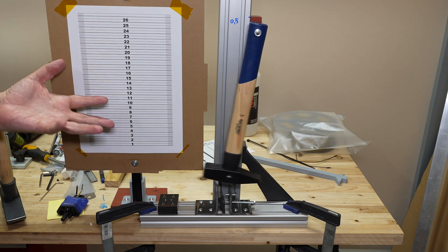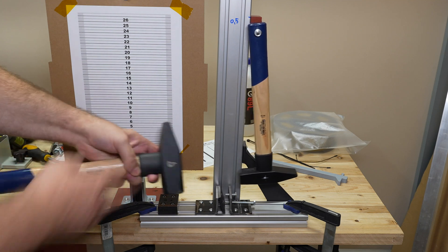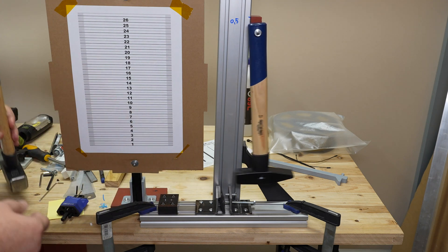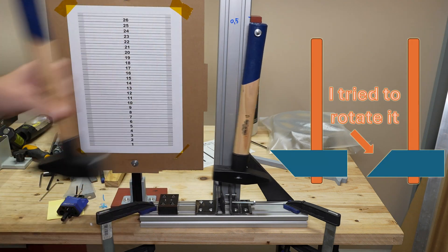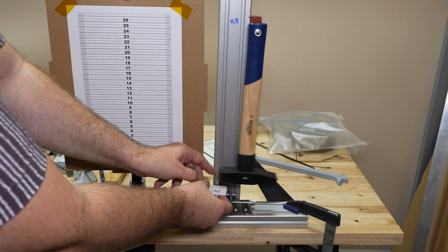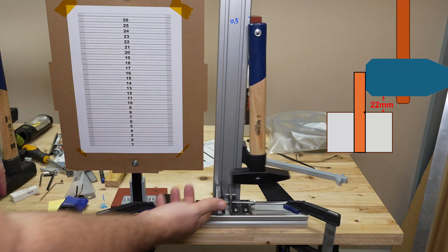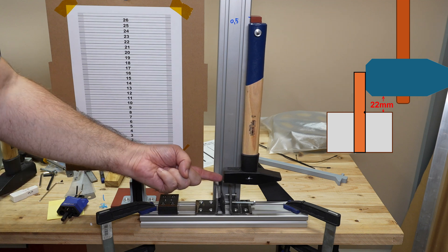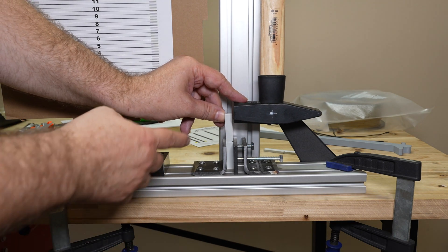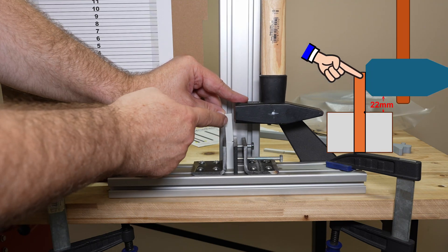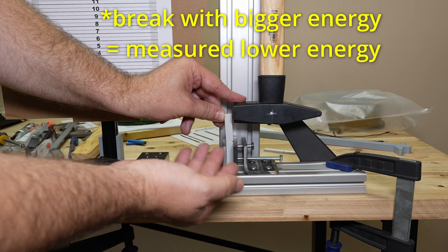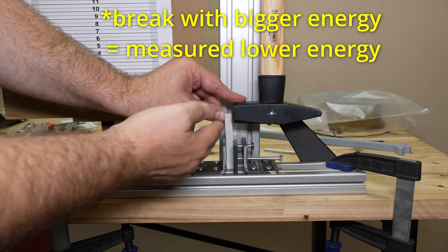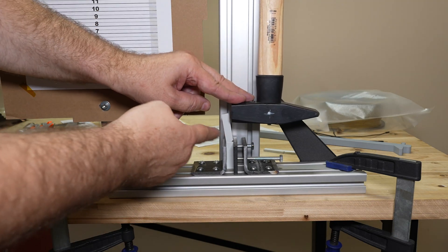Now I want to explain what is the problem with the DIY impact tester. It is not the scale and the measuring method, but the geometry of this hammer. Originally I tried with different hammers. This is the second one. The first one had a very similar structure but it was sharp on the lower side. When I printed a spacer for this hammer to place its correct position, it was 22 millimeters. But this hammer is chamfered, so actually the impact point is a little bit higher. With brittle filaments, this contact point is not only higher because of the chamfer but also because of that flat surface.